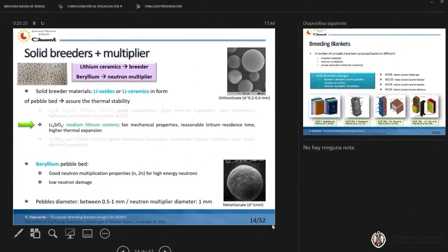They have different properties, but the most important difference is that the lithium orthosilicate has a higher lithium content than the lithium metatitanate, and also a higher thermal expansion. For that reason, I will focus on that, and I will explain it later in a slide dedicated to this material. And as I mentioned, beryllium in the form of a pebble bed is used as neutron multiplier.